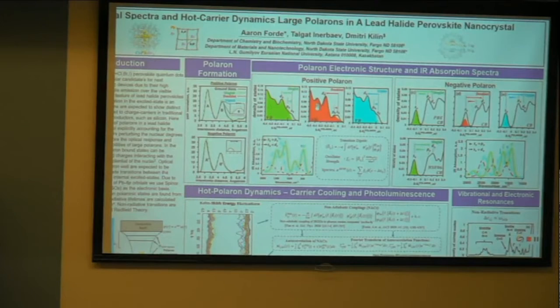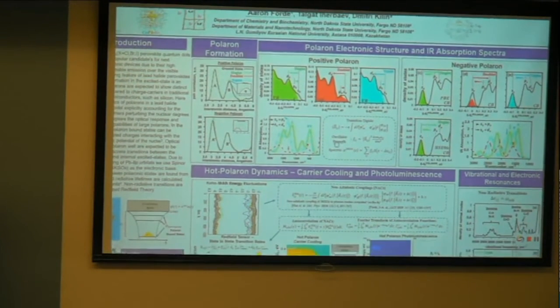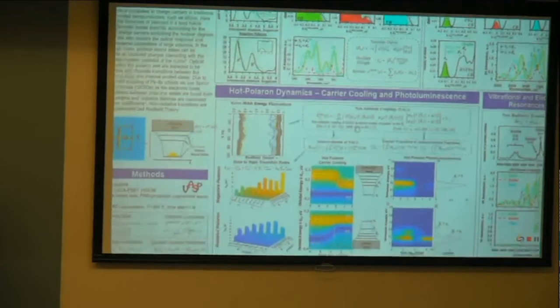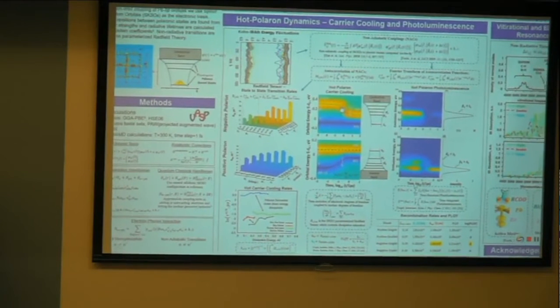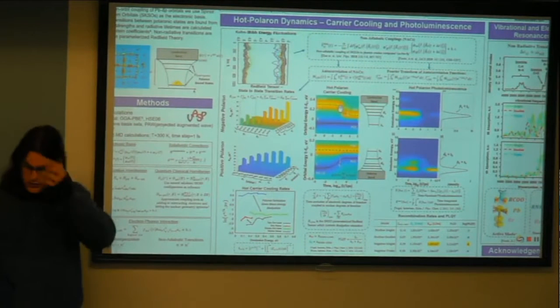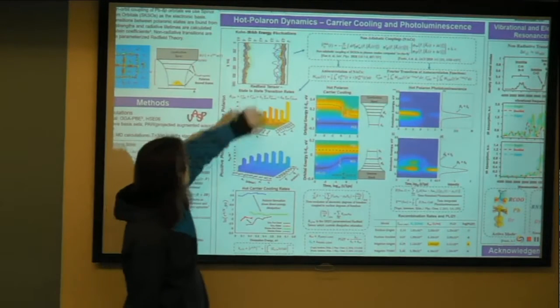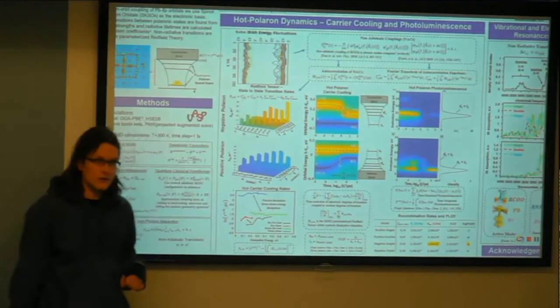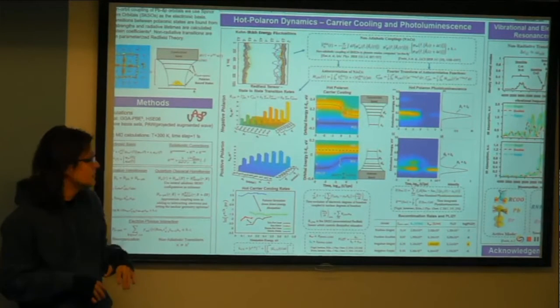So the big takeaway from this is that singlets and triplets are brighter than doublets. And so when we do our excited state dynamics, we focus mostly on singlets and triplets rather than the doublets. So how do we do our dynamics? Generally, to couple electronic and nuclear degrees of freedom, we run ab initio molecular dynamics for each state.